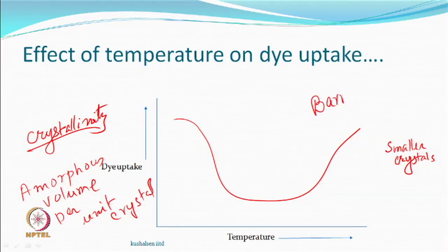When you finally dye the textured yarn, that portion of the yarn is going to take a different amount of dye at equilibrium, even at whatever dyeing temperature you have fixed. The moment you make a fabric out of it, depending on which portion of the yarn comes near another portion, you can start seeing variations which people refer to as barré. As a customer you would like to reject it — this does not look good; you wanted uniform dyeing but the textured yarn is not uniformly dyed.